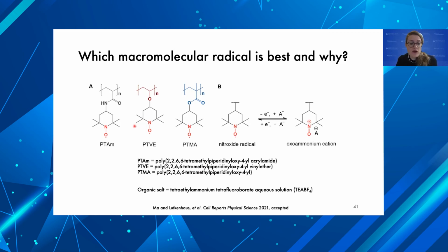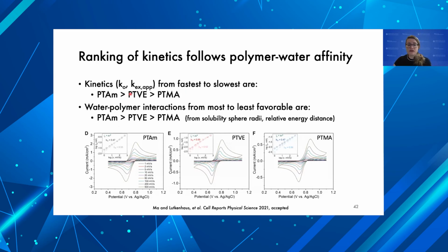To answer that question, we explored a series of 3 radical polymers. You can see they all have the tempo group, but they have subtle differences in the linker group, where you have an acrylamide, a vinyl ether, and then this acrylate, methyl acrylate type backbone. So the redox reaction mechanism is going to be largely the same, but we want to understand when we change these subtle things about the backbone, how does it change the performance? What we found is there's huge changes.